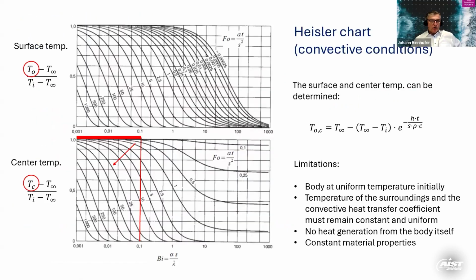An easier solution for convective conditions is to use these Heisler charts. They show you the surface temperature and also the center temperature of a slab. You look at the Biot number, which is shown here on the horizontal axis, and the Fourier number, which is shown in the different curves. You can also see that at Biot number 0.1, the magic number between thin and thick, the center temperature will start to be affected with higher Fourier numbers. Here you have no change in the temperature at the center, and it will only start to grow when you increase the time of the heating process.